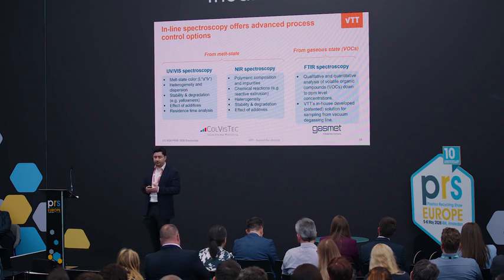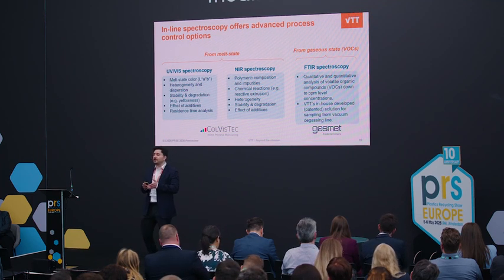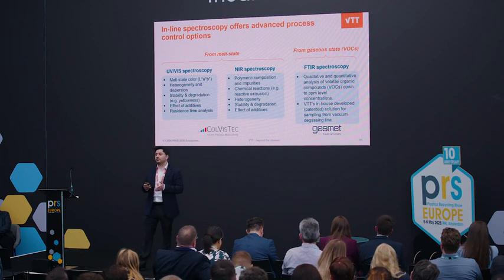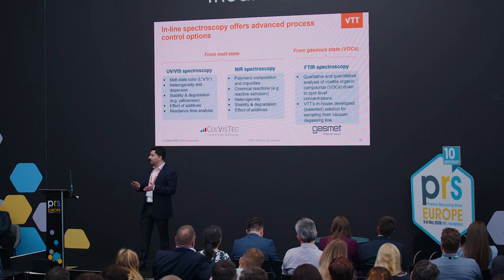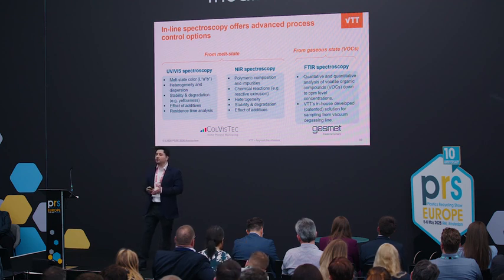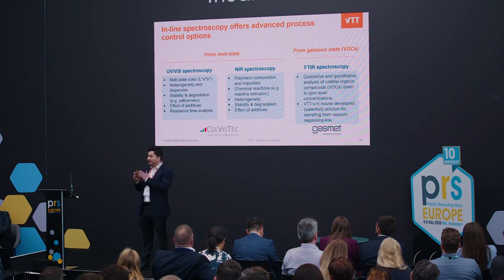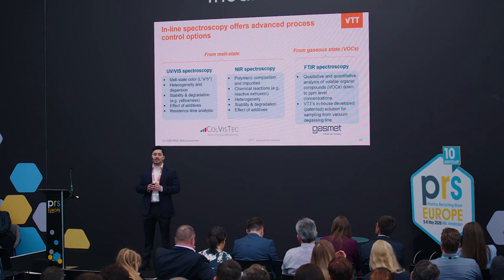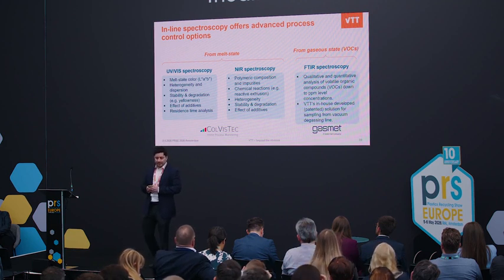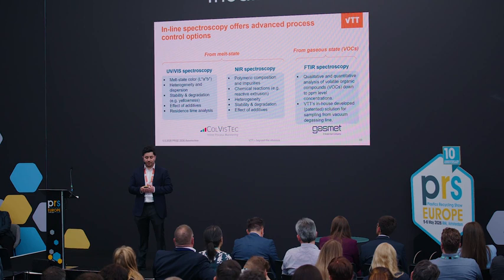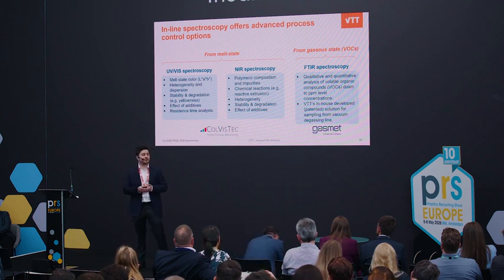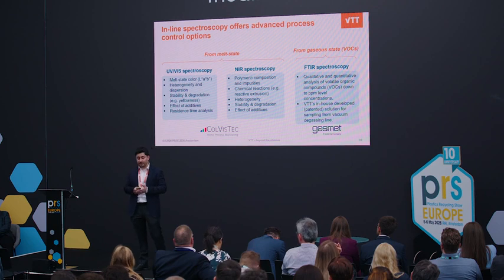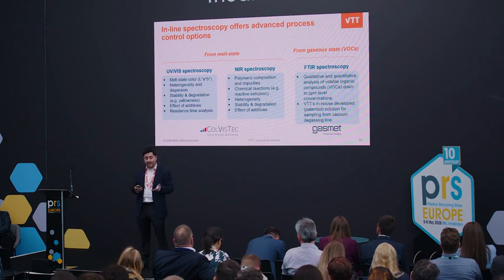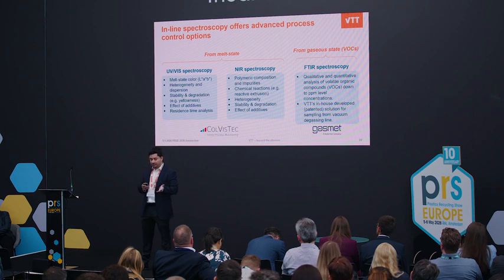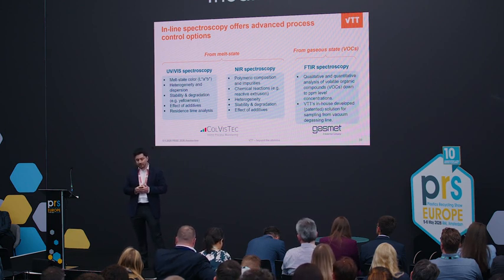With the near-infrared spectroscopy, you go more in depth into the chemical composition. So if you have another polymer type that you don't want in your polymer stream, but you don't know the exact composition of the feedstock either, you run the extrusion, and if you come up with PET composition at some point, it will be shown in the log, for example, in a PP compound. And you will also be able to monitor the chemical reactions if you have reactive extrusion, compatibilization, or other types of reactive extrusions. And you will see heterogeneity, again, stability and degradation. They will be complemented with the UV-vis, and of course, the effect of additives.